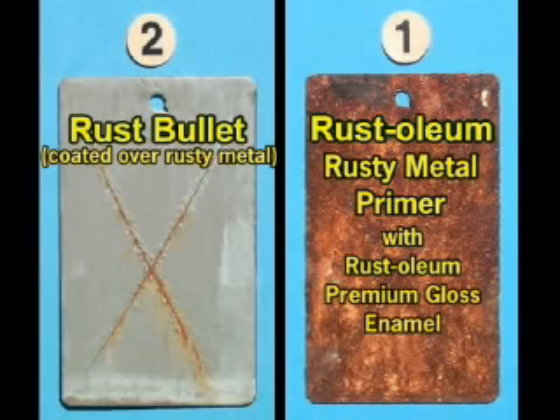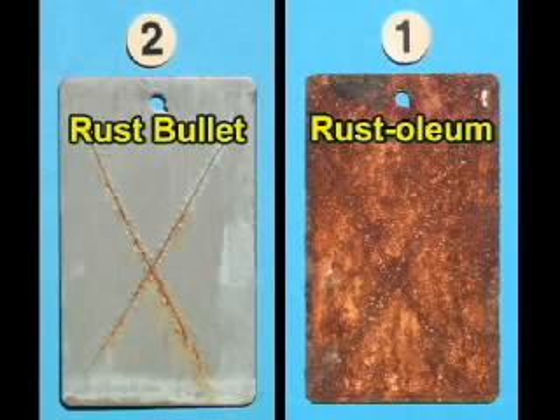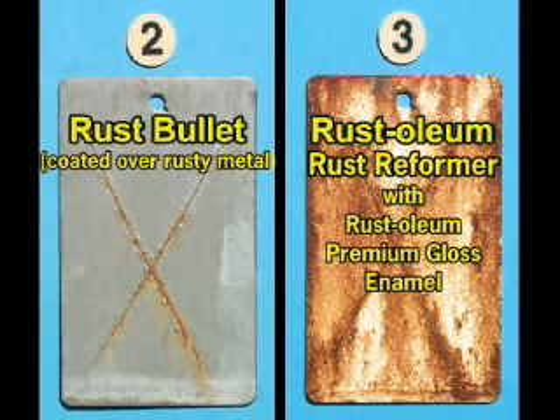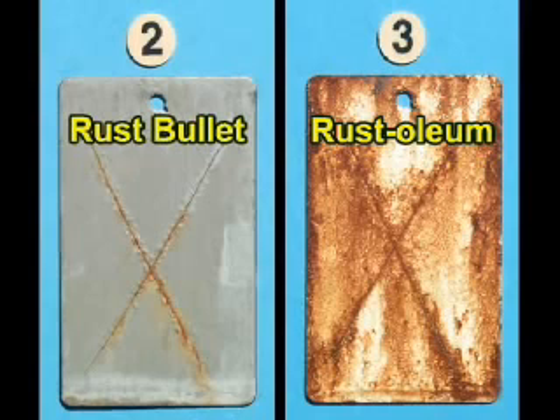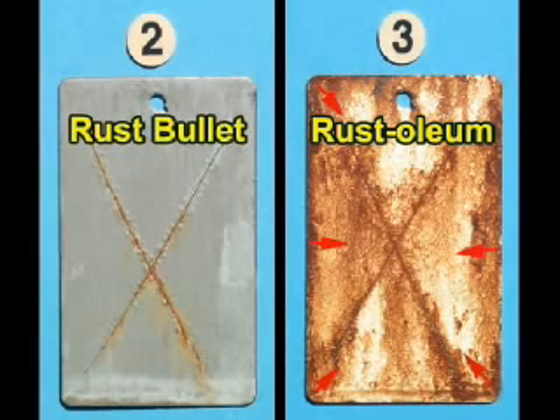This panel was coated with Rust-Oleum's Rusty Metal Primer and top-coated with Rust-Oleum Premium Gloss Enamel. This panel is an approximate 95% failure. Here there is acute blistering, little or no resin retention, and very little pigment retention. This panel was coated with Rust-Oleum Rust Reformer and top-coated with Rust-Oleum Premium Gloss Enamel. This test panel is an approximate 85% failure. There is some resin and pigment retention. There is also a progression of blistering from the scribed lines and edges inward.